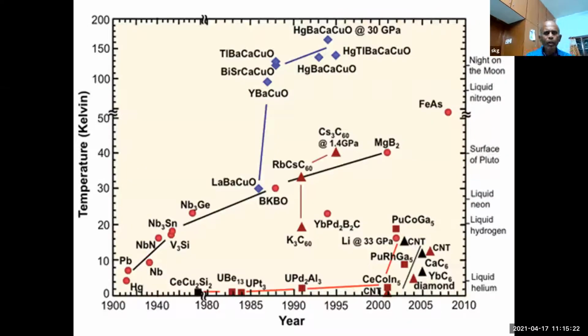So wonderful things happen. Now, when it comes to materials, it all began in 1910 with Kamerlingh Onnes, and people got excited. They found this superconductivity in lead, niobium nitride, A15 compounds, and slowly there was progress. And there was also silent progress in heavy fermions at low temperatures. Then in 1986, there was a revolutionary development. Bednorz and Müller found superconductivity in a lanthanum copper oxide-based material. And then it shot up in the next several months to nearly 100. So the cuprate branch holds a record of about 163 degrees Kelvin in a mercury-based cuprate compound and a thallium-based compound.